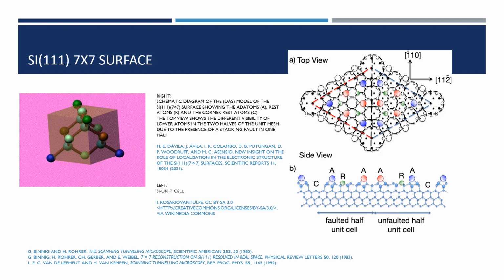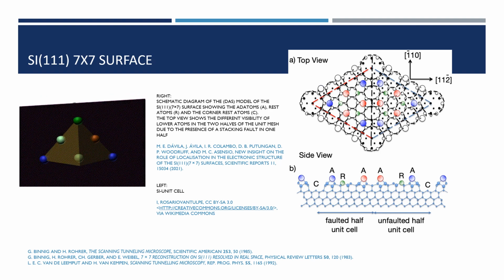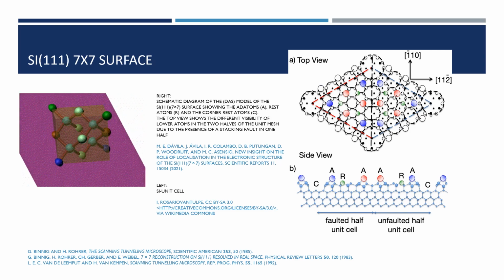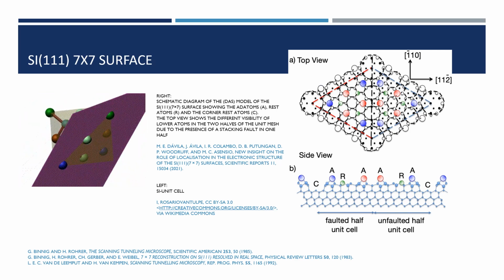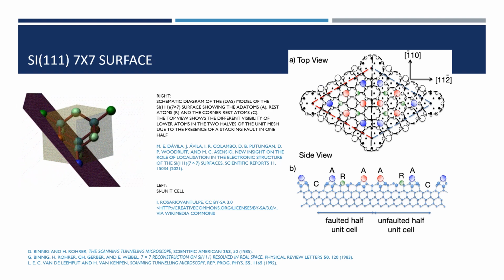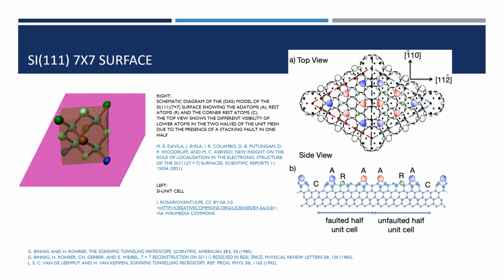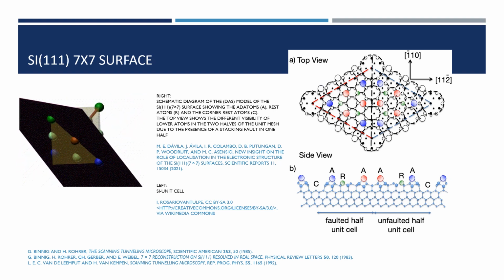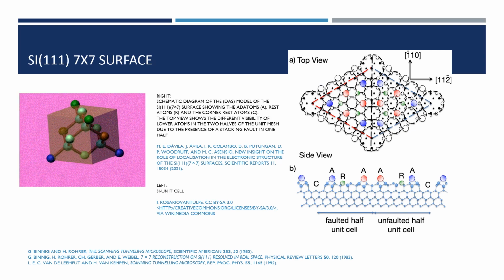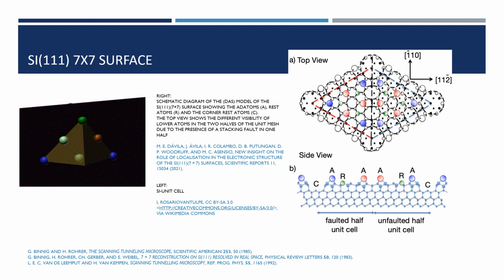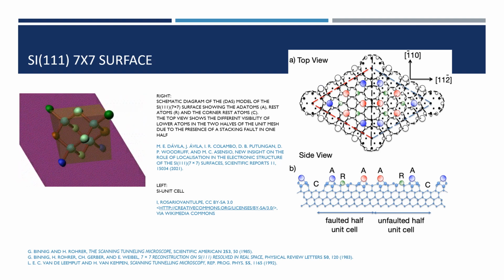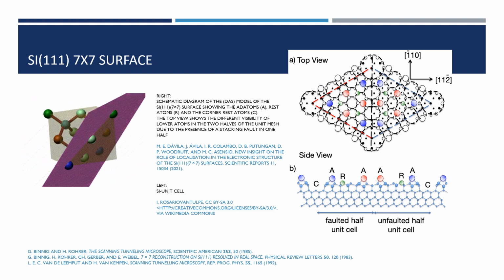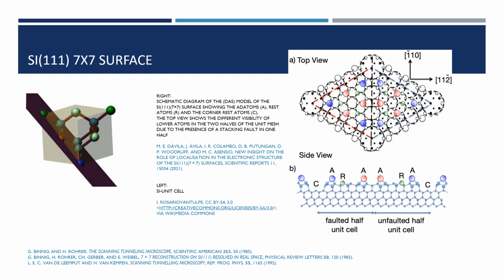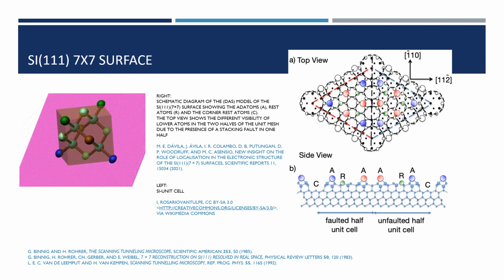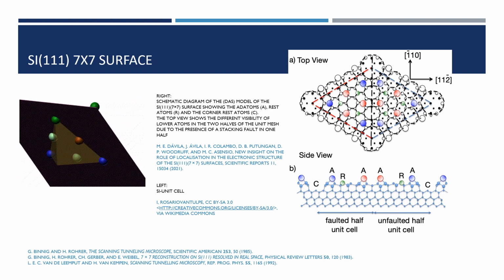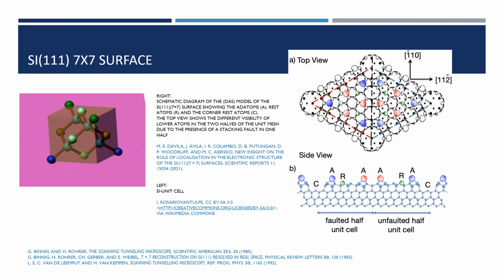To test various proposed models for the 7x7 reconstruction, theoretical STM images were calculated for each of the models. A spherical charge density was assumed at the center of each atom, and the most likely one was the DAS, the dimer adatom stacking fault model, which was consistent with the results of other experiments too. So on the right, as I said, we can see the 7x7 unit cell, and with A there are the adatoms. The rest atoms have a little r, and C are the corner holes.